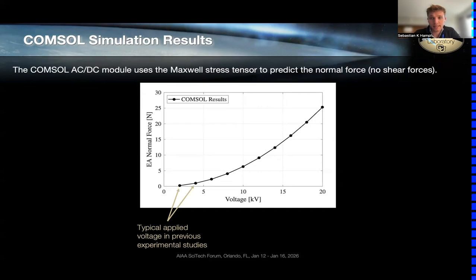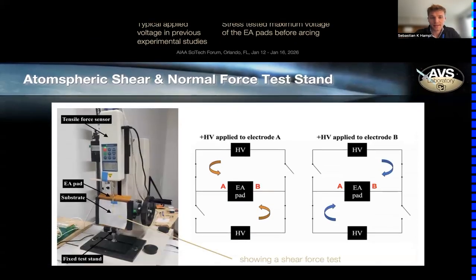As one can see, the EA normal force strongly scales with applied voltage at the pad. And typically, in most experimental studies, the voltages that have been applied to the pads range from 0 to 5 kilovolts. However, it can be seen that it should be very advantageous to apply much higher voltages. And we did stress test our electroadhesion pads and see where they arced. And we could apply voltages up to 18 to 20 kilovolts for both the FPC printed pad and the bilayer pad. So this just allows us to test to way higher ranges than has been previously done, and we expect to see higher electroadhesive forces.